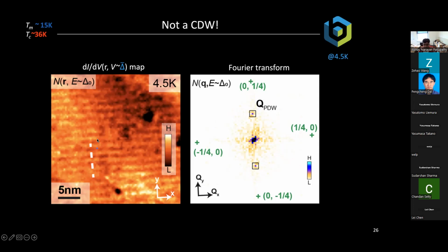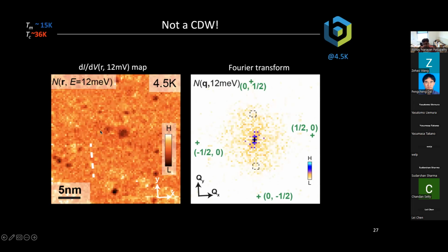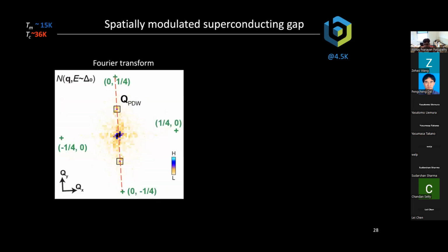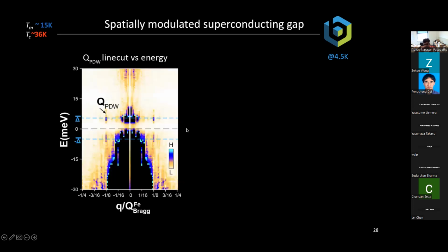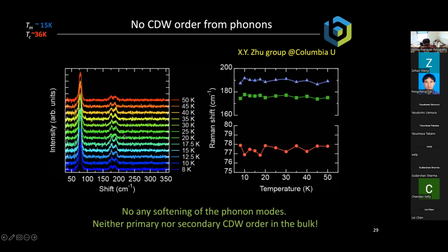On the other hand, in our measurements, we see these modulations only at the superconducting energy scale, only at the energy scale delta naught. And even if you go to twice the superconducting gap magnitude, which is 12 millivolts in this case, which is also fairly low energy, these features all disappear. So it's not a charge density wave from STM measurements. We can look carefully at the energy dependence of the Fourier transform and also confirm this. We also did some other measurements.